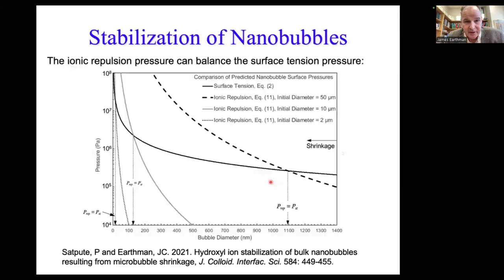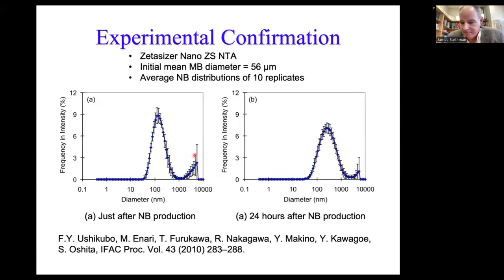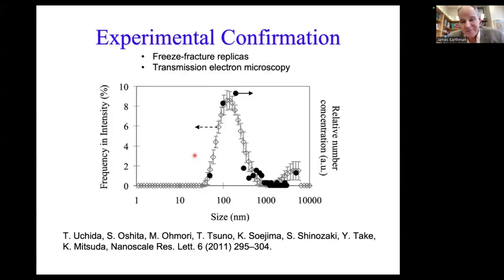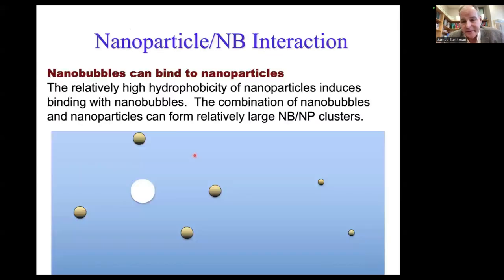Because if you look at our prediction, these two pressures balance at really high pressures. This is in the megapascal range here. So it would take a lot of external pressure to destabilize these things, right? And that was actually one of the criticisms of our paper. And when I explained to them, look, yeah, you can put a lot of pressure on these things, nothing will happen, but look at where they're balancing at. After I rebutted that comment, we got accepted.